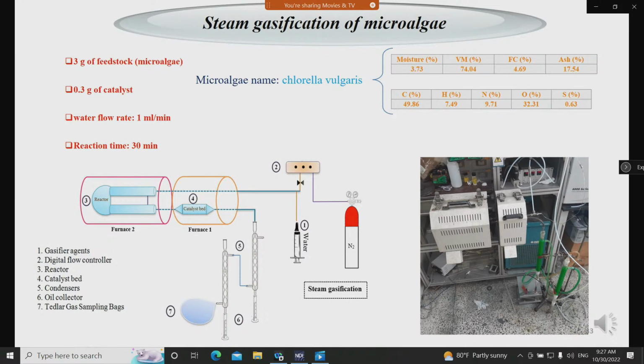Steam catalytic gasification of microalgae was performed using this apparatus. The experimental setup consists of two furnaces. While the first furnace was movable and used for heating the feedstock reactor part, the second furnace was fixed and utilized for the catalyst upgrading.